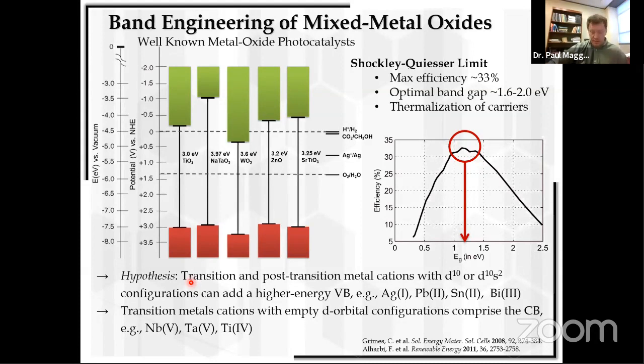And so what we're shooting for is a metal oxide structure which has extended connectivity of both these candidates, silver, lead, tin, combined with the early transition metals, and position them appropriately such that there'll be high carrier mobility in both of those networks, and they can absorb a large fraction of the sunlight, okay? But how do you do this? So this is a synthetic problem, because many of the compounds you would make with these transition metals and main group metal cations have such a small band gap when combined with niobium, tantalum, and titanium that they're often not that stable at high temperatures.